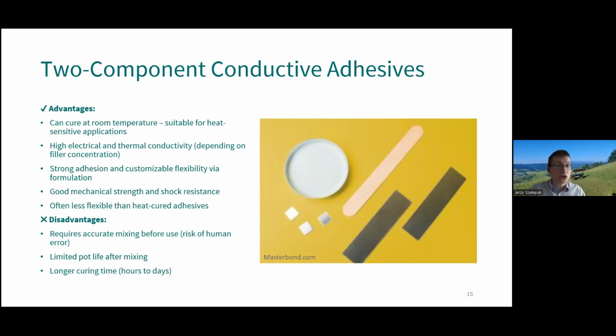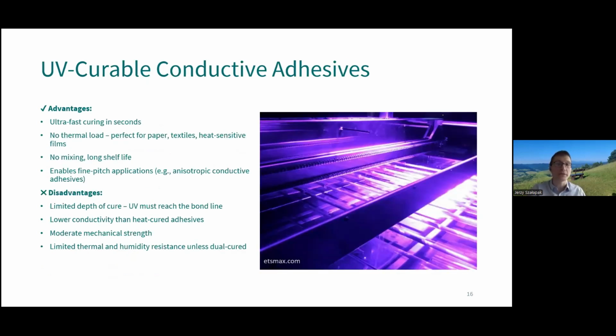The ones that were additionally cured with temperature performed much better both electrically and mechanically. There are more and more materials like that on the market because of the need for low or even room temperature curing. But I personally haven't found yet even one that would be worth using, at least in comparison to the ones discussed before. I presume that is why quite a strong attention is put towards UV curable adhesives. Well, that and curing the adhesives within seconds. That, in comparison to other adhesives, would greatly improve the speed of production of the sample, especially with all the roll-to-roll or rotary screen printing, etc. methods that are crucial for printed electronics.